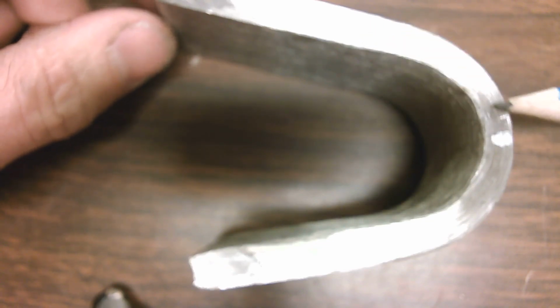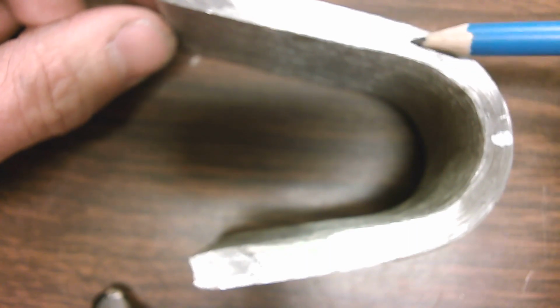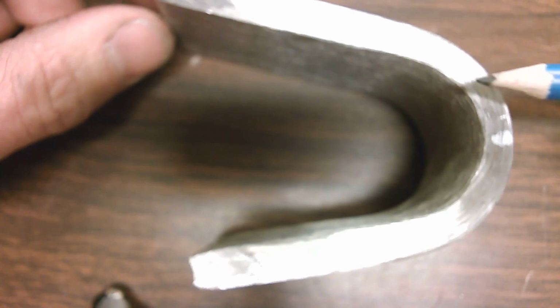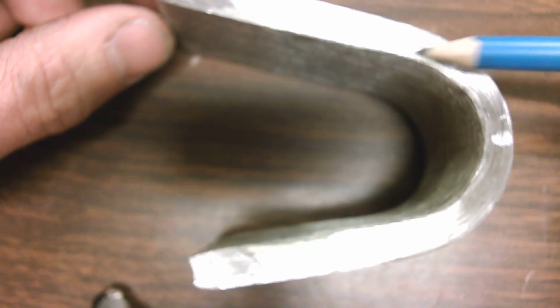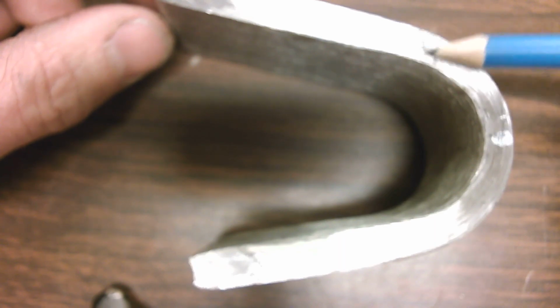So just keep in mind that you really want to make sure you're bending it on the weld. If the weld happened to be up here, and we bent it off to the side, that's not a successful bend test. That's another situation where if that happened for some reason, it's probably because of poor grinding, poor coupon prep after the fact. Maybe ground a little bit too thin in this area, and the weld happened to be up here or something. But in this case, the weld is right here.